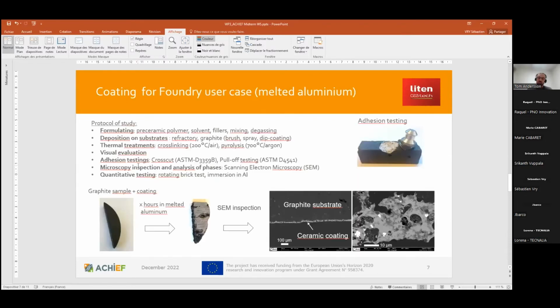Two coatings were developed to match with the use case. For the case of aluminum foundry, the protection of refractory and graphite is done using the same coating formulation. Different deposition processes were assessed: by brush, dip coating, or spray coating. Thermal treatments are done in two steps.